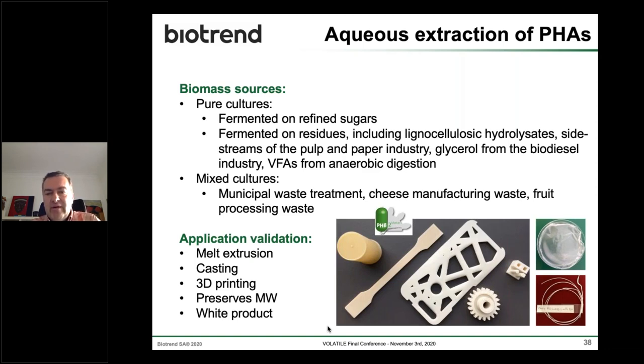And I would like to point your attention to the picture in the middle. In this picture, you can see two parts on the left-hand side, which are a bit yellowish, and the remaining parts are white. So these yellowish parts were produced using the commercial PHB on the market, whereas the white parts were produced using the polymer purified at Biotrend. And for the plastics industry, this makes a huge difference, because in the white part you can put any pigment you want, and you can color the part the way you want.